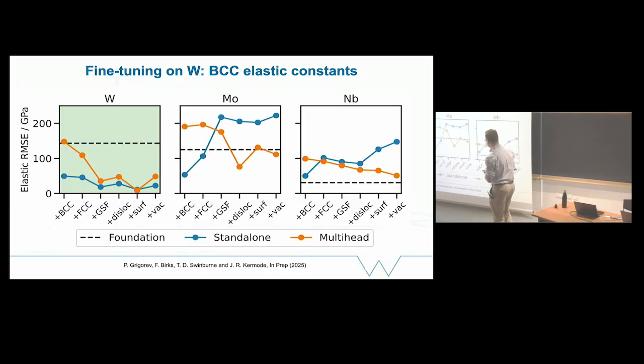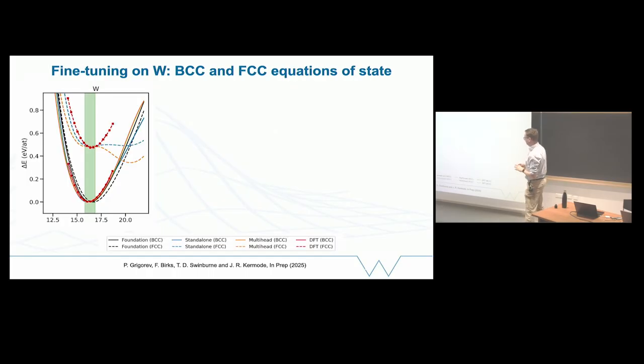But what's nice is that if you use the multi-head approach, despite not really adding any data on deformed molybdenum or niobium configurations, it does actually get better, or at least not much worse, than the foundation model was for those. Whereas if we fit just to the tungsten data, then of course we get worse on the other ones. So that was quite nice to see.